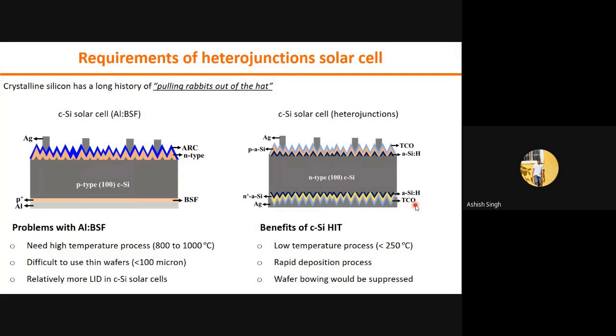an electron transport layer. A benefit of this heterojunction solar cell is it requires a low temperature process, meaning we can make the solar cell below 250 degrees Celsius. Due to the low temperature process, the production output will be high compared to the crystalline silicon based. And due to the low temperature process, the wafer bowing problem which was observed in the aluminum BSF solar cell is suppressed.